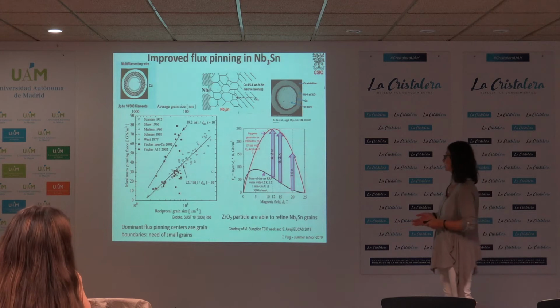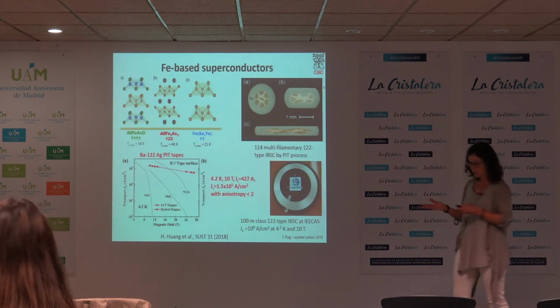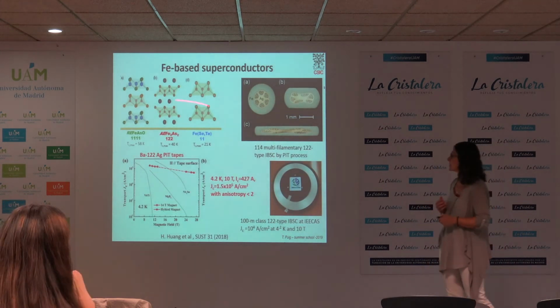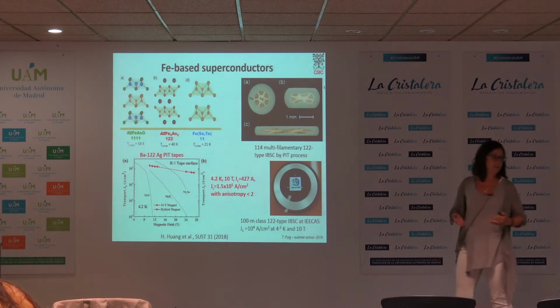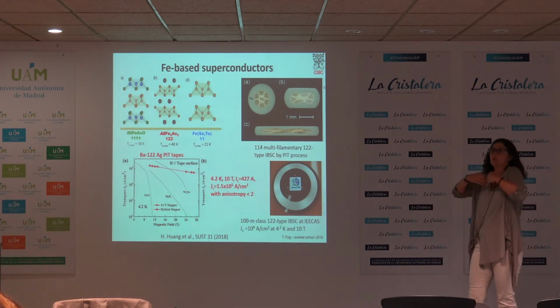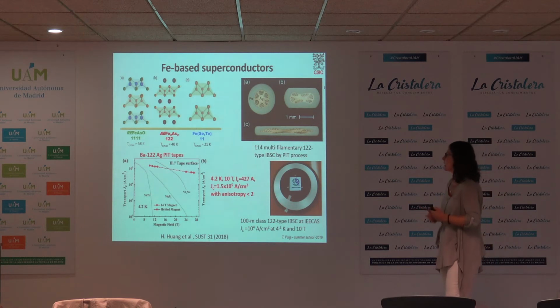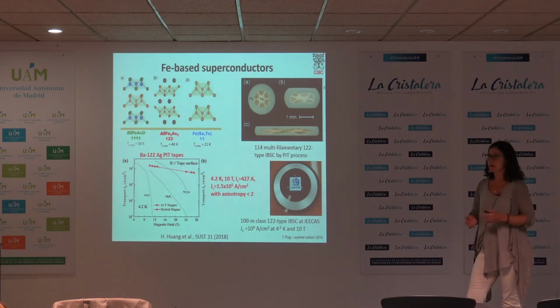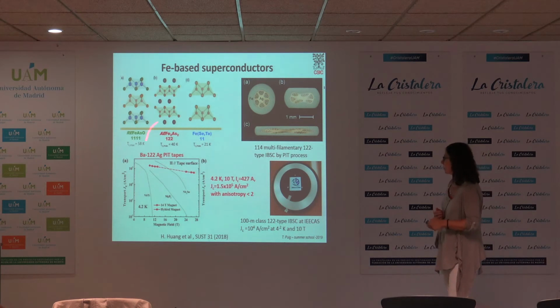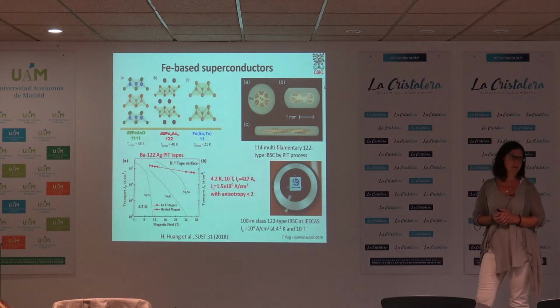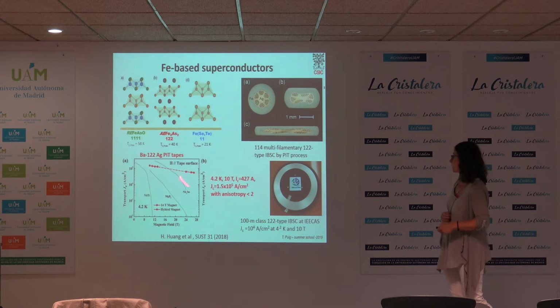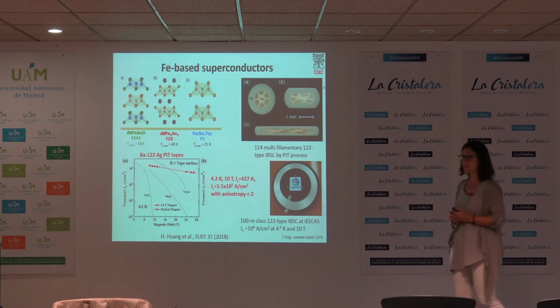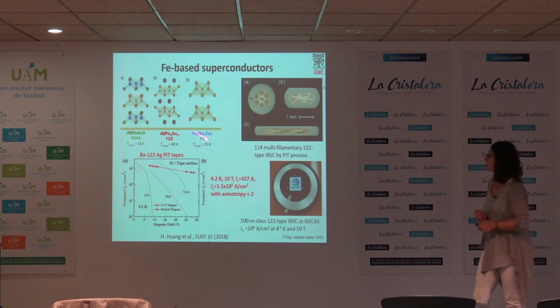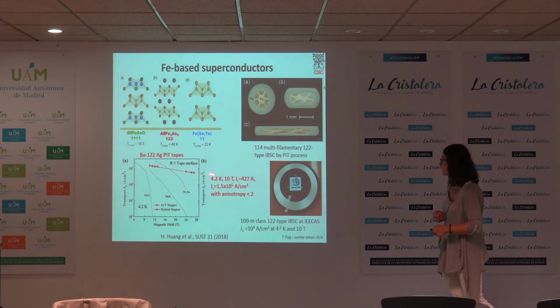In the case of the iron-based materials, it's known that there are many phases and many interesting physics. It has been possible to make single crystals and thin films, but it was really a problem to make wires. Nowadays, also with the 122 phase, it's possible to make wires with very high critical currents, already in the range of 10 to the 5 at 4.2 kelvins, and therefore even getting better values than the niobium-tin material.